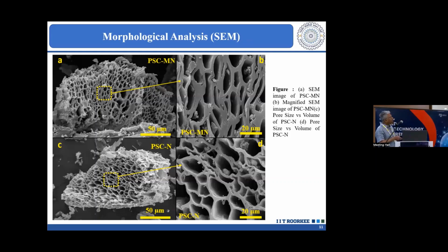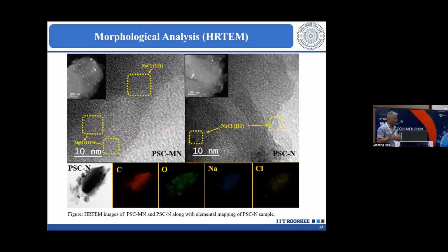Then this shows the FESEM microscopy, just to look at the porous structure with higher resolution, so you can see the honeycomb structure. So this mesoporous solid helps the sodium storage and the easy movement of the sodium when it is in contact with the electrolyte. So this is the basic morphology of the structure, and this helps in the good mobility of